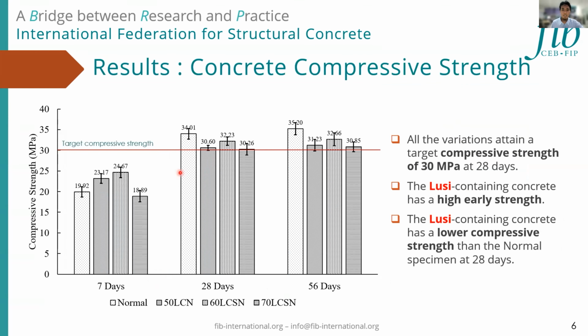And next is the concrete compressive strength test. The result of the concrete compressive strength test shows that the Lusi variant has a good early strength in 7 days. Although the Lusi-containing concrete exhibits high early strength, its compressive strength is lower than that of the normal specimen after 28 days. However, all variations had achieved the targeted compressive strength of 30 megapascals. There was no noticeable difference in age from 28 days to 56 days, which indicates that the concrete mixture has run out of materials to hydrate.